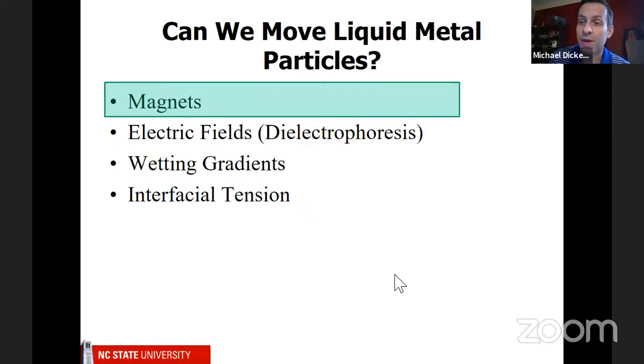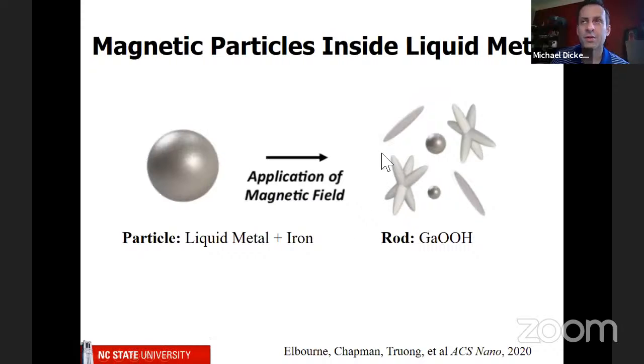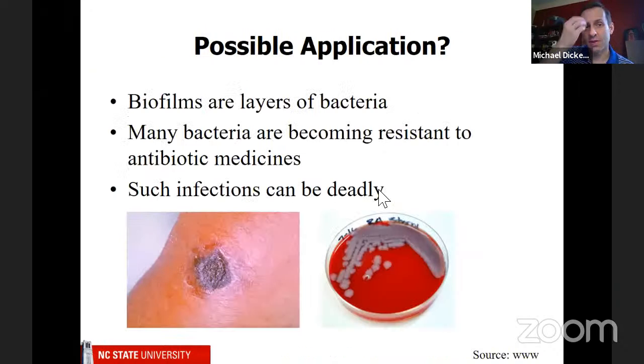So in the first way, we use magnets. And what we do is we take the liquid metal with some iron powder. So these particles have a little bit of iron inside of them to make them respond to magnets. This was done by my friends in Australia. And so I contributed only in a very small way. So the names you see here are the people who led this work. So anyway, if you apply a magnetic field, this was kind of interesting. These particles actually become rods, and they somehow spin around. So one possible application of this is to kill bacteria.